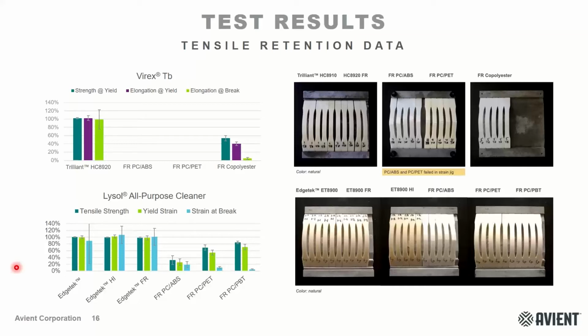And then for your test group, you'll be treating that with the disinfectant, and you'll compare the tensile properties. You do that by dividing the test group by the control group, and that'll give you a percent retention value. So what you aim for in this test is 100% retention. Going above that or below that could be equally bad things. The values we look at here are strength at yield, elongation at yield, as well as elongation at break. So these are telling you the failure points of the material.